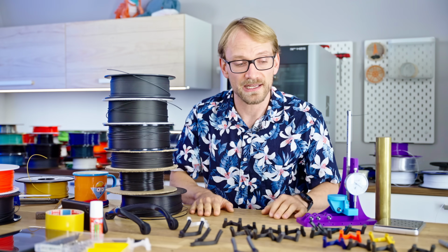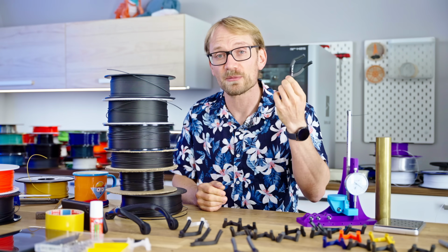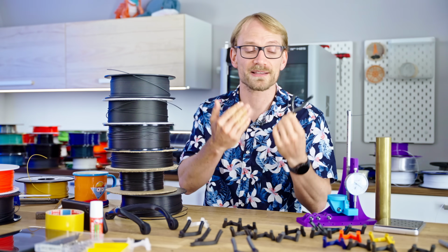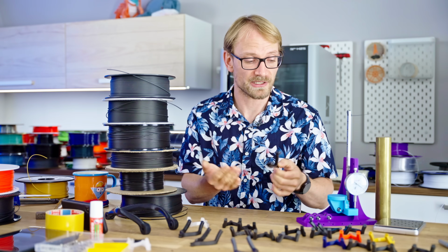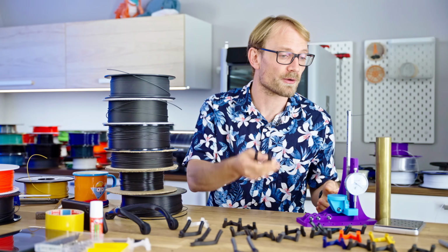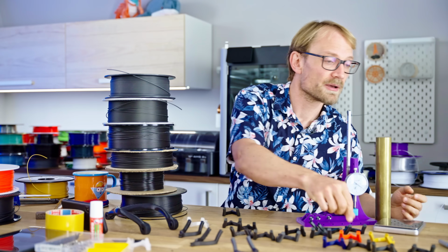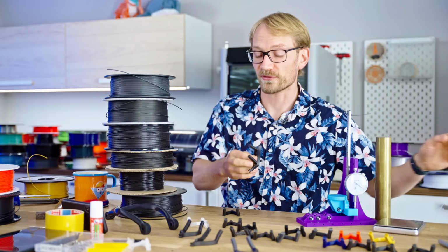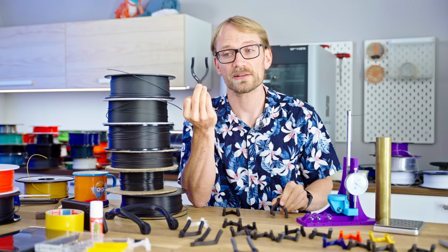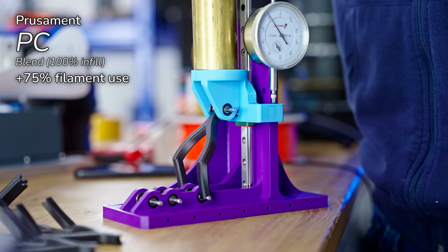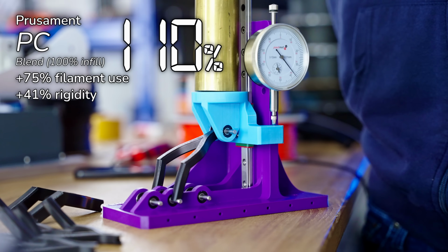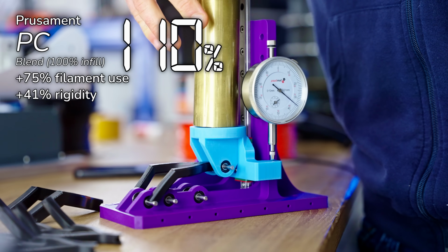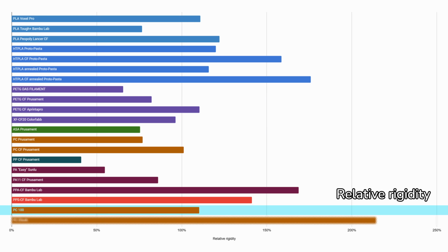The real kicker here is that we're 3D printing. We are not limited to this exact setup and this exact geometry even, because we can design these parts pretty freely. So I did 2 more things that I think put all of this in context. First of all, I just printed the same part with 100% infill versus the 15% that I used in all the other parts. I did that with the Prusament polycarbonate. And this used about 75% more filament and gave a 41% improvement of rigidity. So if that is all the space you have, then yes, adding more material does make your parts more rigid.